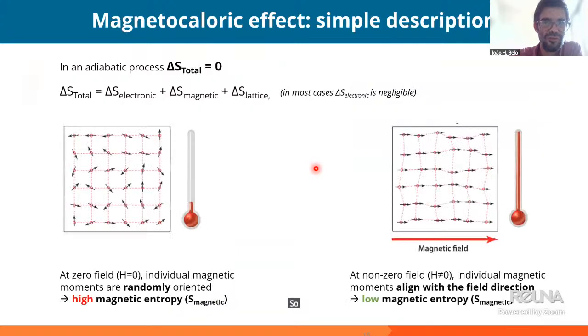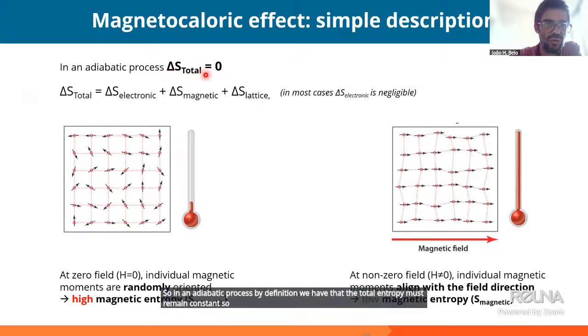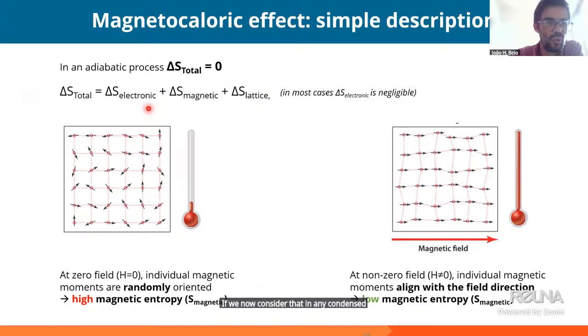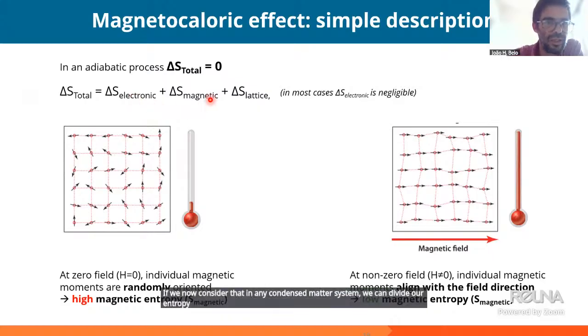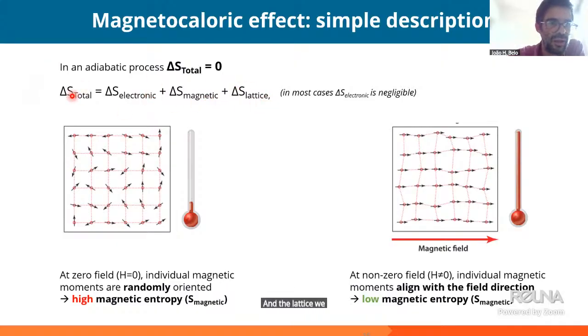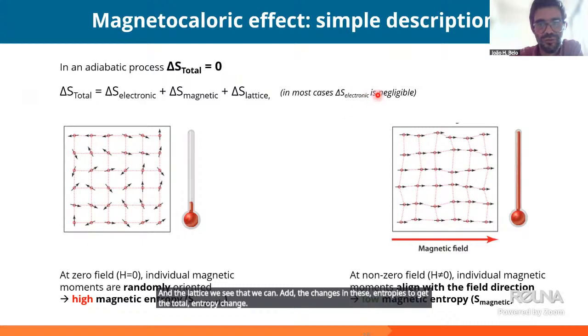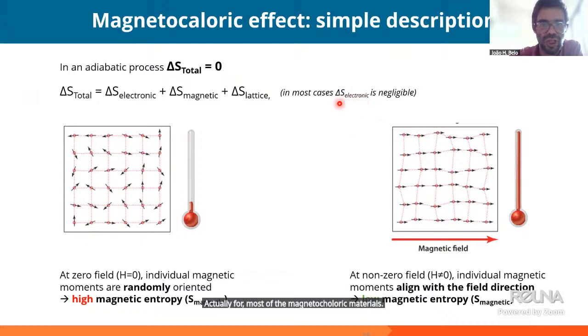So these are the two most important thermodynamic properties to quantify the magnetocaloric effect. So now, trying to give a more atomistic but yet simple description. In an adiabatic process, by definition, the total entropy must remain constant, so the change in total entropy must be zero. If we now consider that in any condensed matter system, we can divide our entropy into three major reservoirs, the electronic, the magnetic, and the lattice, we can add the changes in these entropies to get the total entropy change. Actually, for most of the magnetocaloric materials, the change in electronic entropy can be negligible. So we can just consider the magnetic and the lattice.